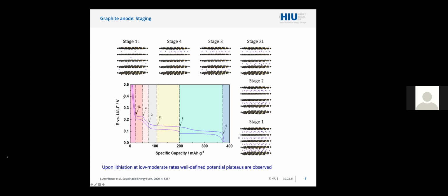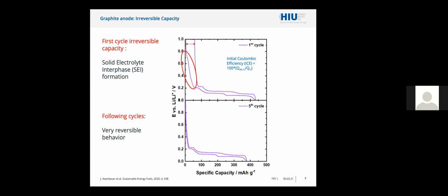You also notice at the beginning there is a very different behavior from the rest of the discharge and charge curve. And actually, this is something very important that happens in graphite, and it's what is called the first cycle irreversible capacity. There is a certain amount of charge which flows into the cell at the beginning that goes specifically into the solid electrolyte interface formation. This is needed. When it's well done, it occurs only in the very first cycle, and in the following cycles, a very reversible behavior is observed with only the typical staging mechanism occurring for the lithium insertion and extraction.